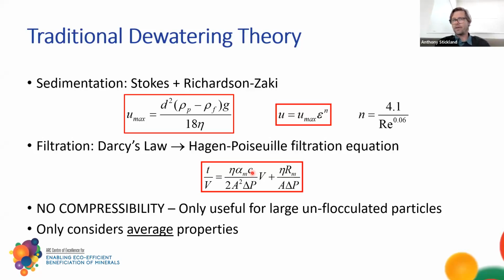Likewise, c is a process-dependent parameter that depends on the initial concentration and the cake concentration, but that is also a function of pressure. And so you can't use this equation if you've got something that varies a lot with pressure, is essentially the message. So it doesn't take into account compressibility, and so it's only useful for large unflocculated particles. As soon as I have some very fine particles where surface roughness or non-spherical shape starts to have an effect, or as soon as I've got some significant interparticle adhesion, then I end up getting compressibility,